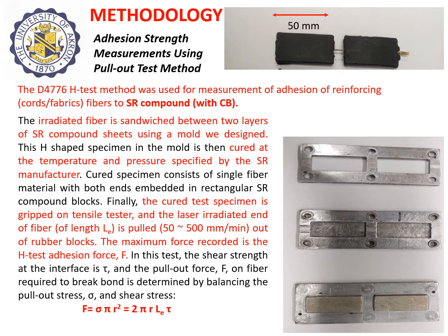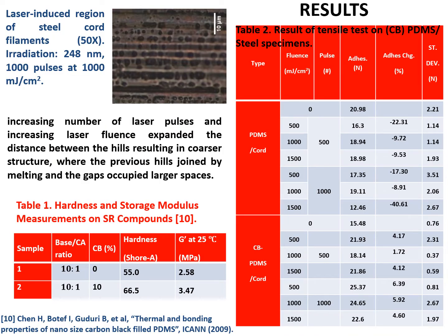You can see the rectangular matrix coupons, each of which is 50 millimeters in length. This is gripped on both sides in the grips of the instrument testing machine, and the fiber is pulled out. The pull-out condition is modeled by using the classical equilibrium condition, where the interfacial shear stress tau in this equation on the bottom represents the adhesion strength. Le is the embedded length. R is the radius of the fiber or the cord. And sigma is the stress that develops in the fiber by the force F, which is the pull-out force which we measure.